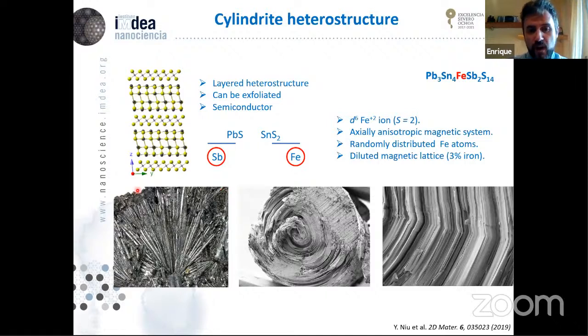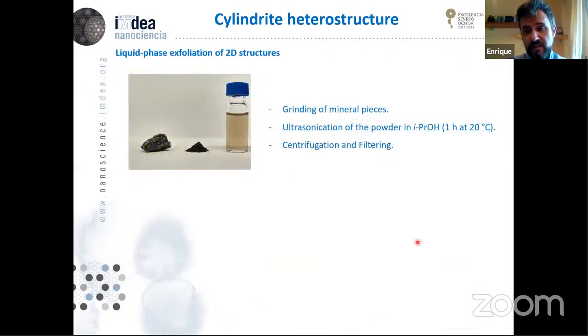Well, the reason why this material is called Cylindrite, I think, is quite obvious, right? Because it crystallizes in these cylinders. Here in these images, you can see also that it is a layered heterostructure. So what we have basically done is to exfoliate these materials using a liquid phase exfoliation.